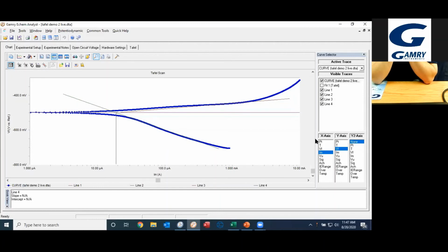If you can't observe the surface, then you can start looking at things electrochemically, and you can run any number of different experiments. Actually, you can just observe your OCP value over a given amount of time, see how that's changed. You can run impedance on it and probably pull out parameters there and see how those have changed.